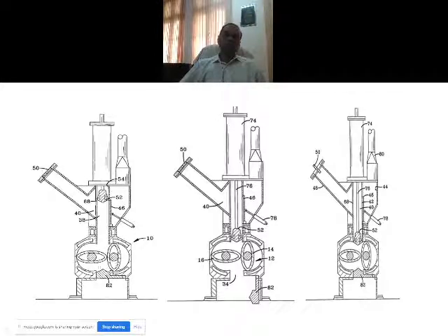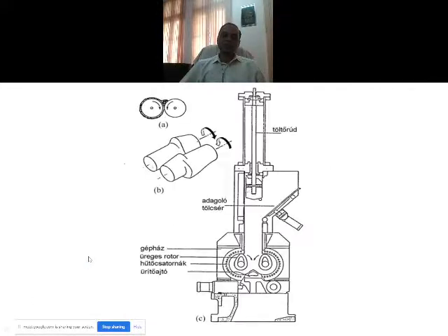Now one thing you'll remember is, the chamber volume here, if you subtract the volume of the rotors, you get a certain volume there. If you take that as V0, you will not fill the chamber with V0 material. The volume of the material that you put will be anything between 65 to 90 percent of the available volume. That's called fill factor. That depends a lot on the type of mix, whether it is a master batch or is it breaking down.